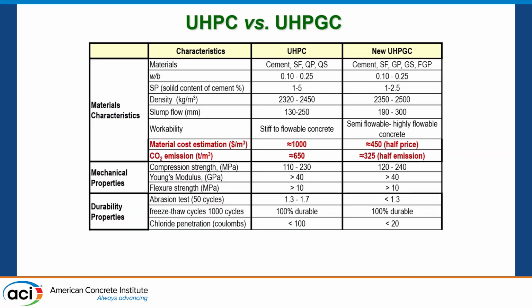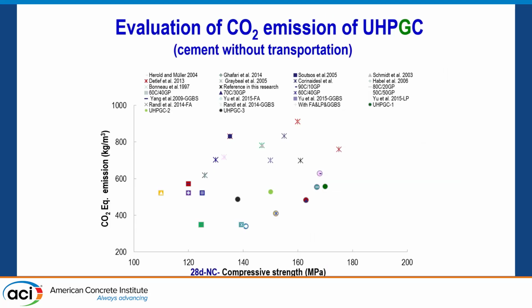And here, those are very basic calculations of saving on materials. This is just a simple calculation done by Nancy of her materials. You can see that you decrease a lot of the material, of course, to mitigate CO2. But then we did more detailed work where we compared many UHPCs, the standard one and the ones where we replaced it by fly ash or slag, whatever. So those are the classical UHPC.